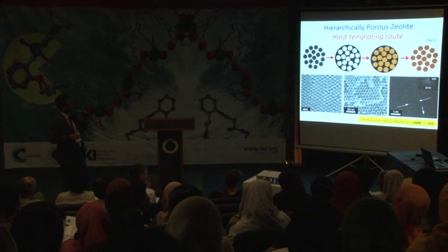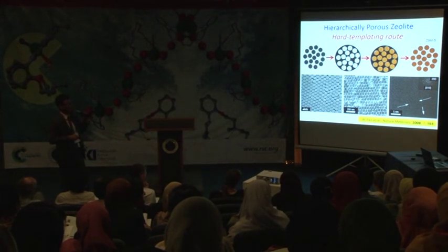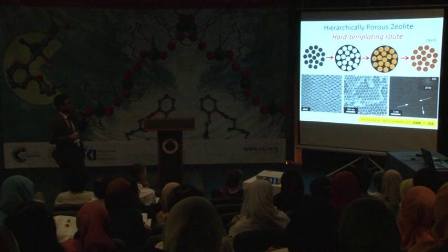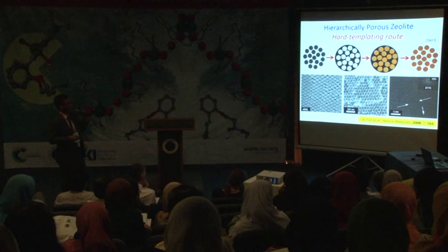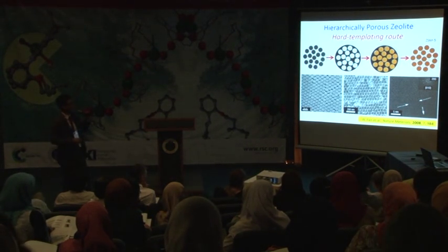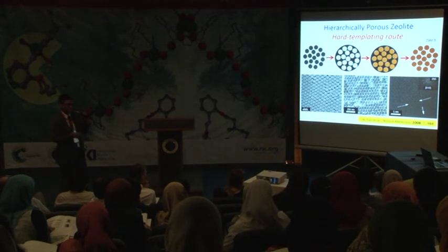So the silica was removed, and then within this hole, they used this as a reactor to synthesize zeolite. This is the zeolite, probably ZSM-5, one of the most famous zeolite type structures, synthesized in these so-called carbon reactors. And then they remove the carbon, they can get the zeolite in monodispersed size. And also the hierarchical porosity can be obtained through the interparticle space.